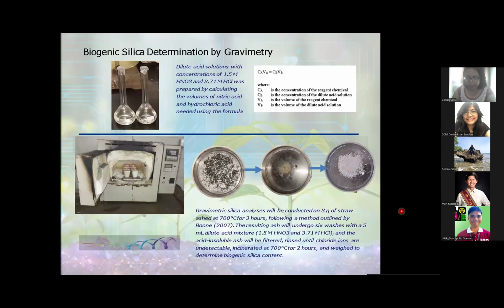So this is the biogenic silica determination by gravimetry. First, the dilute acid solution, which is important for washing the contaminants. 1.5 molar nitric acid and 3.71 molar hydrochloric acid was prepared by calculating.